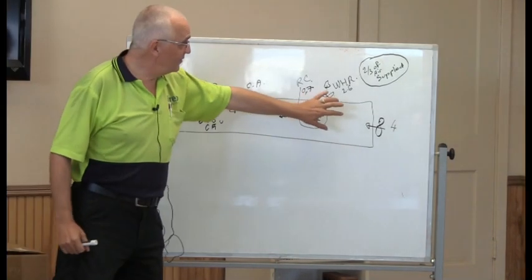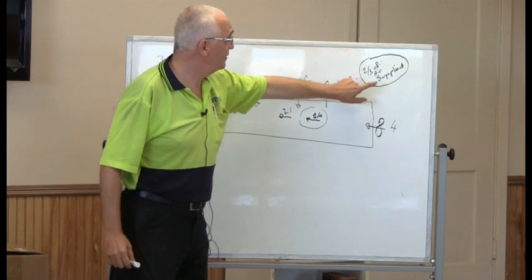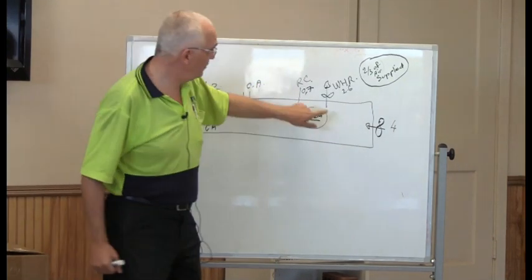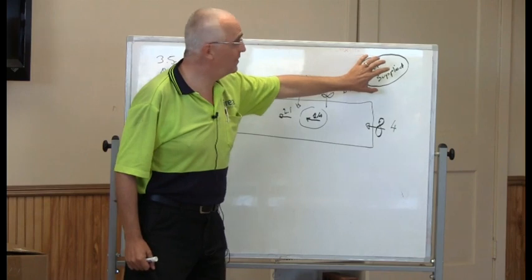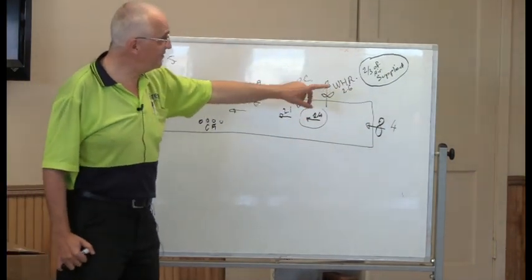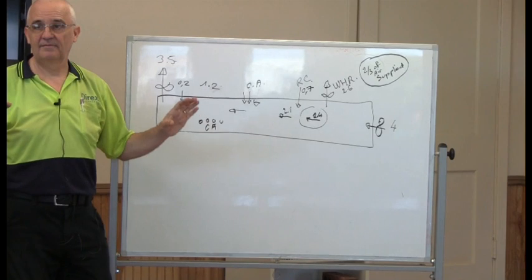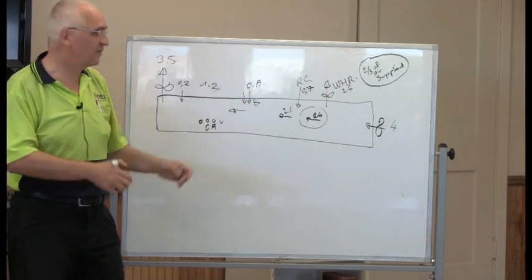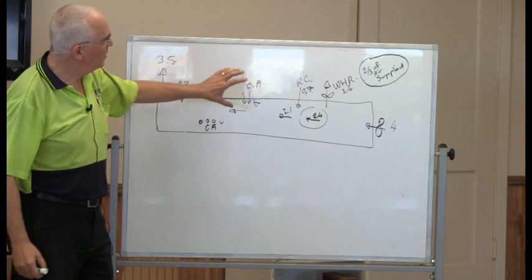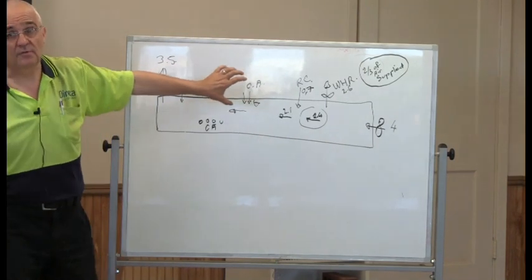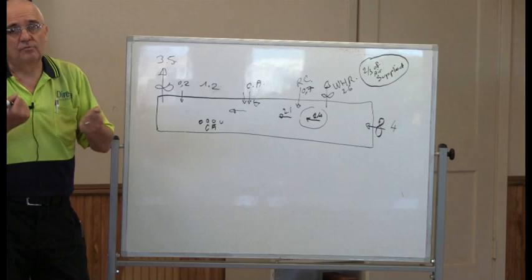For me, the biggest thing to remember is this versus that, and that ratio. Not the value itself, but the fact that what I do here and there, and their relative flow. If I have this part right, I have 80% of my kiln properly running, because this becomes the foundation on which everything else works. Because there is not much you can do on the combustion air unless you have 200% excess air. There is not much you can do on that intake. You know, the rapid cooling still has to do its work.